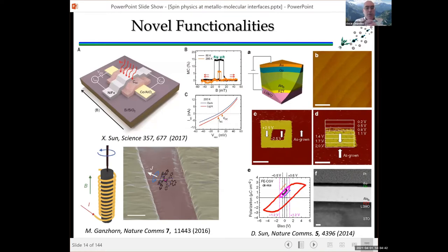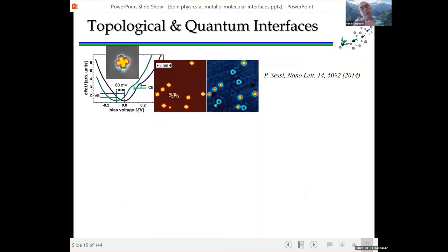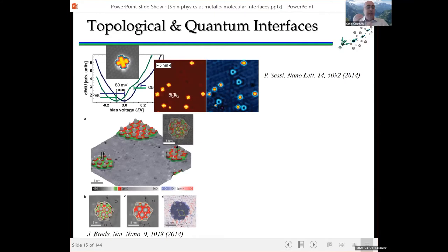If you want to go into more topological and exotic quantum structures, then we have, for example, the work of Mirko Cinchetti, where he could shift the conduction and valence bands of topological insulators, in this case, bismuth telluride, by using phthalocyanines. Or we can also have the work of Wiesendanger and colleagues, where they studied the topological spin textures, skyrmions in this case, when they put different carbon allotropes. It's not quite C60, but they are part of carbon cages and graphene and other carbon allotropes, and study the magnetic coupling.